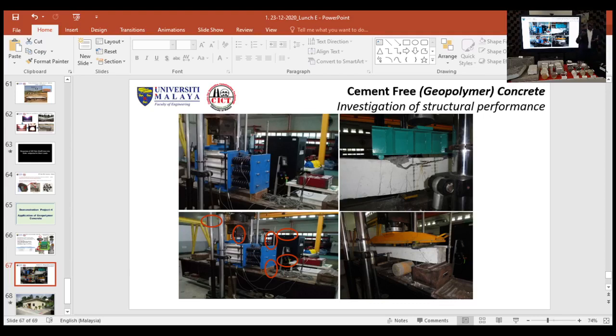We can even get high strength concrete or medium strength concrete, low strength concrete, depending on the binder content and the mix design. So these are some of the investigations. You can see the shear resistance and the flexural resistance have been investigated, and we have found that this concrete is at par with the conventional concrete.